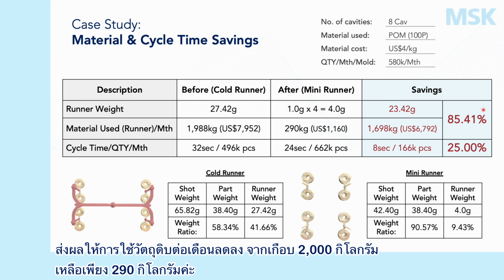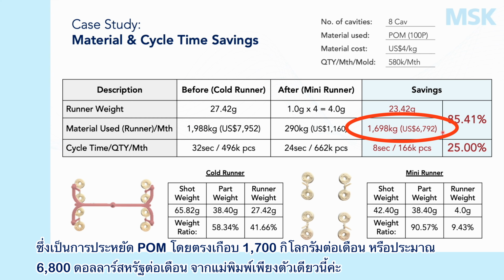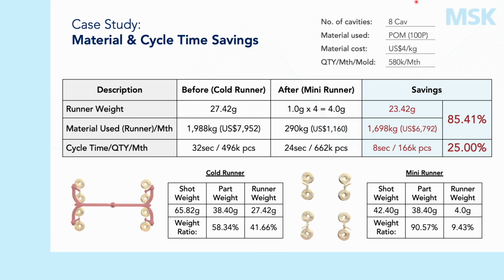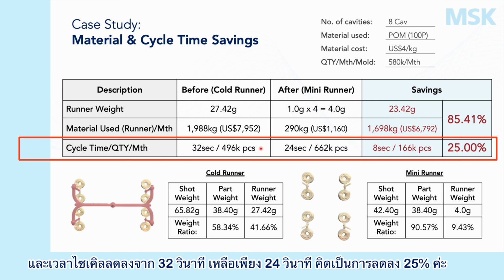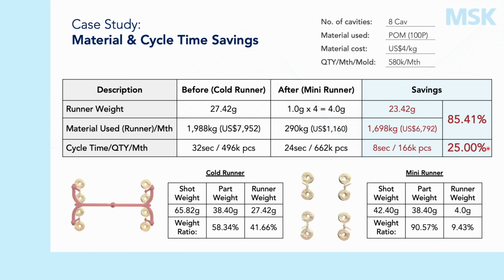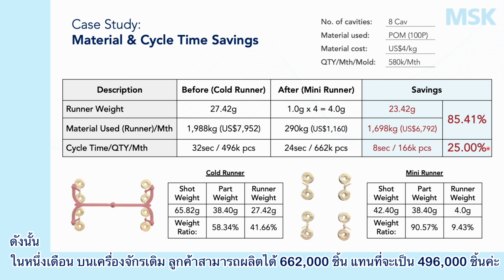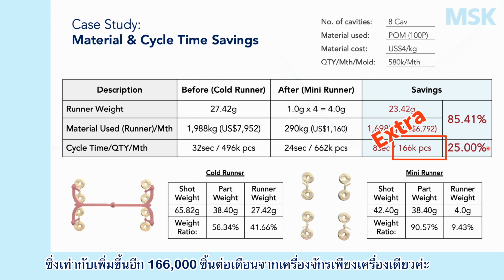That translated into monthly material consumption. They went from nearly 2,000 kilograms of runner material a month down to just 290 kilograms. That's a direct saving of almost 1,700 kilograms of POM every month, which is about 6,800 US dollars every month on this one mold alone. And the cycle time came down from 32 seconds to just 24 seconds, a 25% reduction. So in the same month, on the same machine, the customer produced 662,000 parts instead of 496,000. That's an extra 166,000 parts per month from one machine.